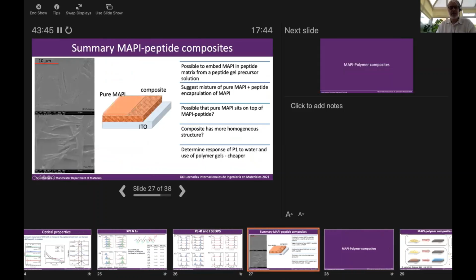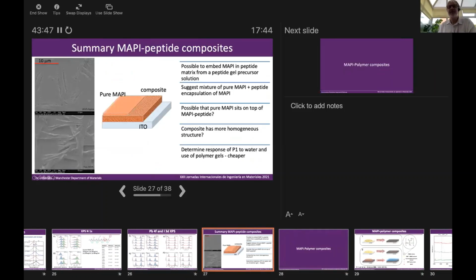Okay. So just to summarize this section, we found that it is possible to embed methylammonium lead iodide into the peptide matrix using a peptide gel precursor solution.